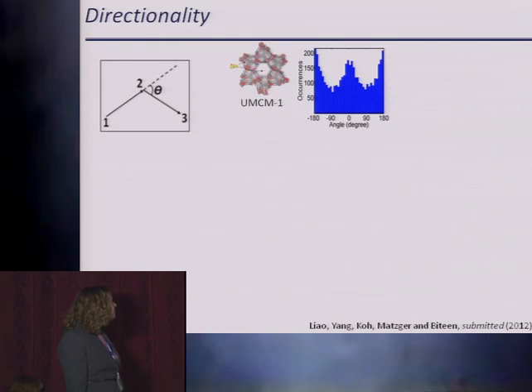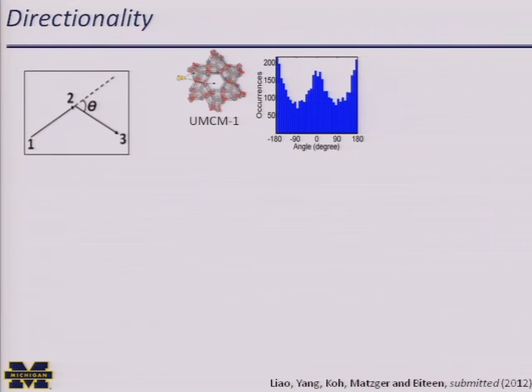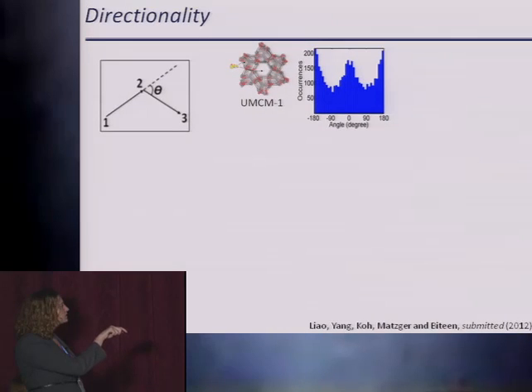We look at the directionality by doing an angle analysis. So for every step, if we go from 1 to 2 to 3, we measure angle theta. If theta is 0, that means we're moving straight forward. If theta is 180, we're moving straight backwards. In UMCM1, with its linear channels, we see the following distribution. Most of the motion is either 180 degrees or 0 degrees, so the motion is linear. It's mostly moving forward or backwards.